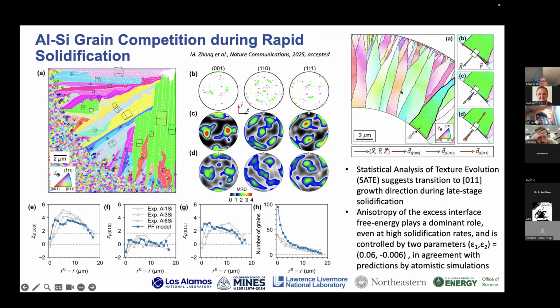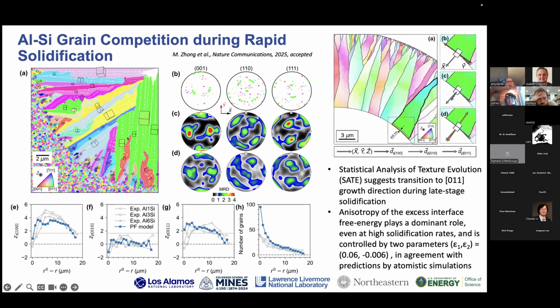And then if we couple this with post-mortem characterization, so here we're doing crystallographic mapping in the TEM, we can get the texture evolution with time and again start looking at things like grain competition. So this is an example from some new work that just got accepted to Nature Communications and should be coming out pretty soon. Basically we're looking at that grain competition and the texture evolution with time during rapid solidification. And one of the neat things about this is we came up with a statistical analysis approach to look at the grain competition, and the results suggest we have a transition to 011 type growth during late stage solidification. And this is tied to anisotropic effects, especially of the excess interface free energy, that plays a dominant role.